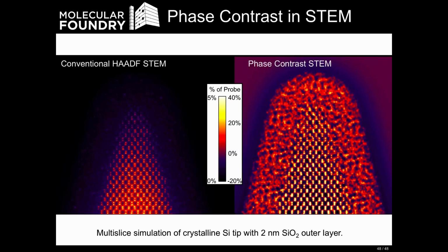But if I could take a phase contrast image of this sample, and this is the same simulation but using a phase contrast imaging method, and I'll talk about the details of this in a couple slides here, we can see a much higher signal to noise here. And that's because now our total signal region is going from about -15 to +35%. So we're using 50% of our probe instead of less than 5% of our probe.